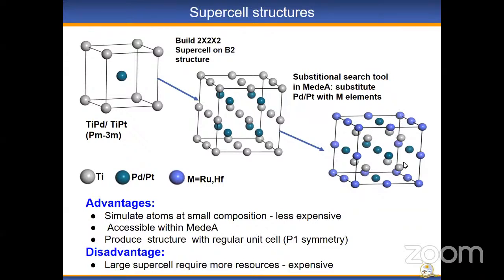But importantly, this needs to be checked. All the configurations must be checked to satisfy yourself that the energy ranking is low or high. So the supercell approach is one approach that we have used successfully to predict some new alloy systems. However, I should point out that the calculation could be very expensive, especially when you use a large supercell, and that's where you need the high performance computing at the CHPC to assist you to do this kind of calculation.